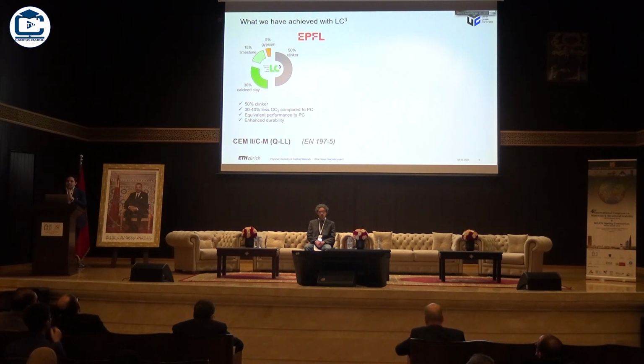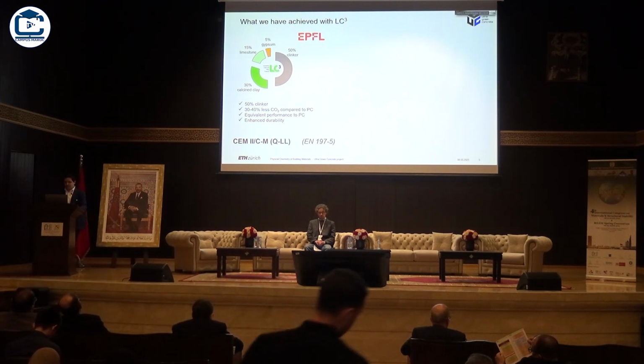So very important in this pathway to low carbon concrete is LC3, and what we have achieved with LC3 is remarkable. This is a project that has been led for the last 10 years by EPFL in Lausanne in Switzerland, and it's basically a blended cement, so we are still talking about Portland cement-based materials, which combines clinker, calcined clay, and limestone at a 50% replacement ratio, basically allowing us to save between 30 and 40% CO2, and most importantly, achieving equivalent performance to Portland cement and enhanced durability, as Karen detailed.